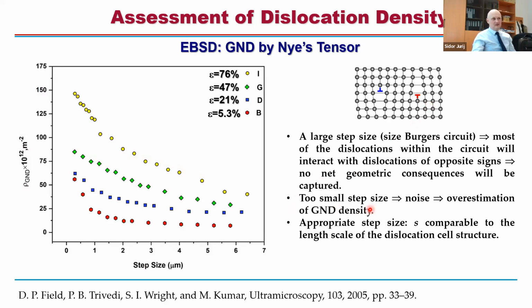When you have too small a step size, you will run into another type of problem, which is called noise. So you will have overestimation of GND density. In fact, this problem was observed almost 2 decades ago and published by David Field and co-authors. What they show is that you have overestimation or noise at very small step sizes and underestimation at large step sizes. And then the question is, what should be the appropriate step size?